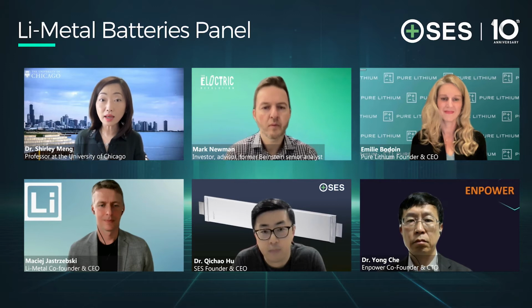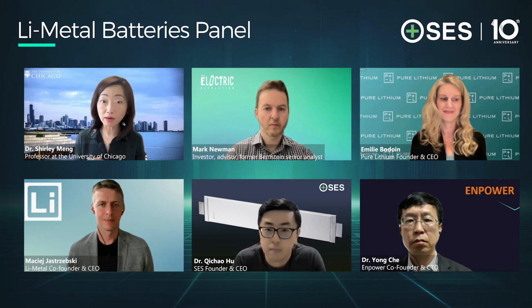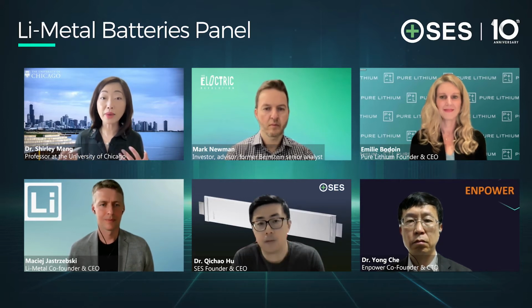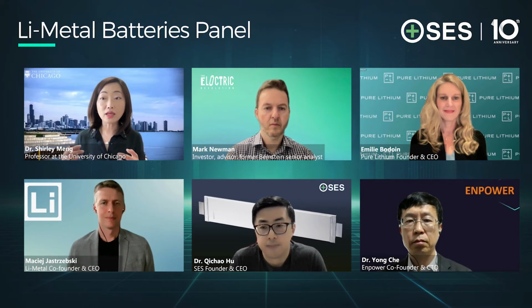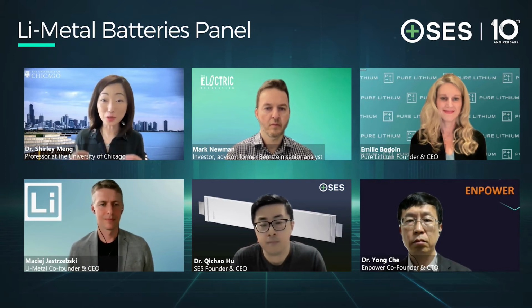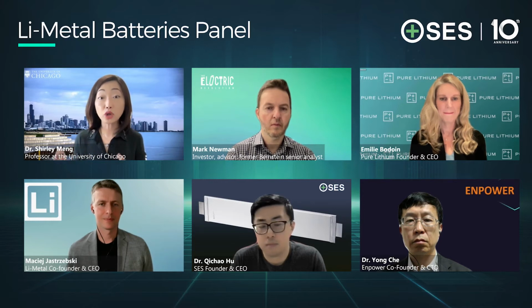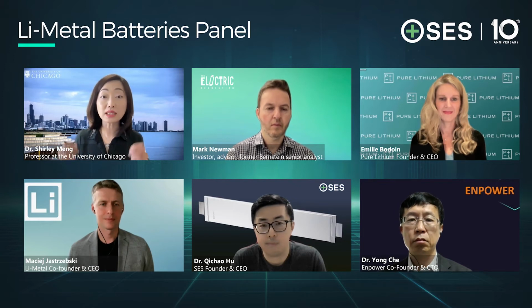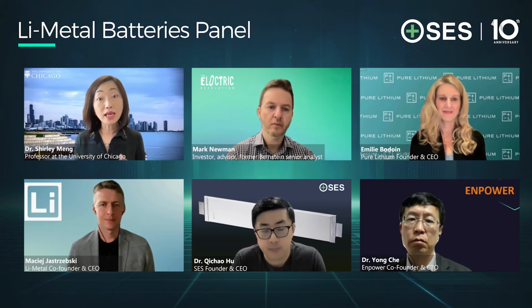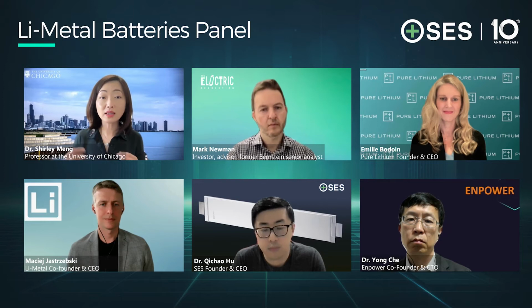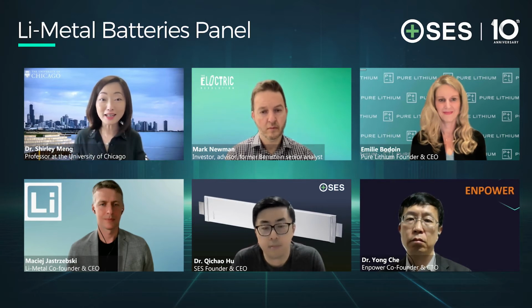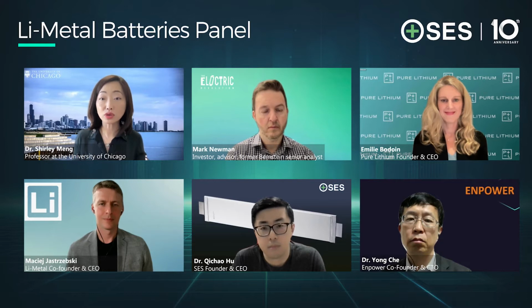So let's talk a little bit about silicon. I think the challenge with silicon is that so far we have seen in liquid electrolyte compatibility studies with lithium metal that there is 99.9% compatibility, highly compatible electrolytes with lithium metal. We are having a lot of challenges finding a compatible electrolyte with high silicon loading, more than 78% silicon loading, to be extremely stable in liquid electrolytes. So if I think about the longevity of cycle life, this electrolyte compatibility is the key. That's why, in the anode race between lithium and silicon, I have to give kudos to the people who work on lithium metal, because they really worked out how to find a good electrolyte for lithium metal.